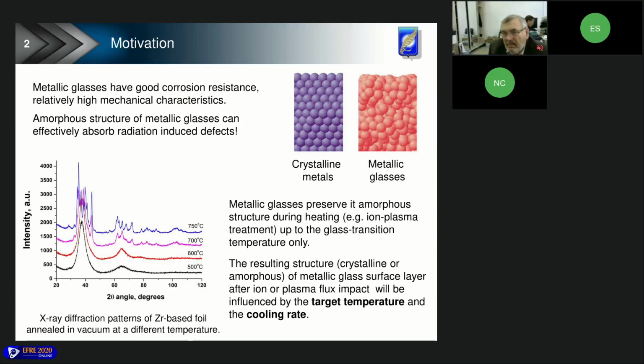the metallic glasses preserve their amorphous structure during heating only up to the glass transition temperature. This temperature depends on the type of material and the cooling rate during material synthesis. The glass transition temperature is usually about 0.4 to 0.6 of the base material melting temperature. So heating of metallic glass above this temperature results in the appearance of local crystalline areas or full crystallization, resulting in accumulation of radiation damage and worsening radiation resistance.